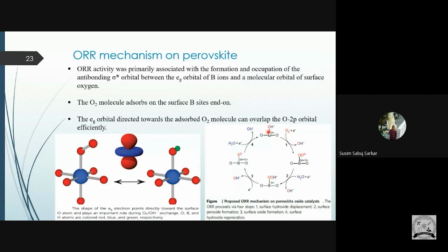So everything will depend on the strength of the B-O bond and how the oxygen is forming the bond with that B atom, that means the transition metal atom. The B atom is actually a transition metal atom, and an O2 molecule adsorbs on the surface of the B site end-on, and the Eg orbital directed toward the adsorbed O2 molecule can overlap with the O 2p orbital efficiently.